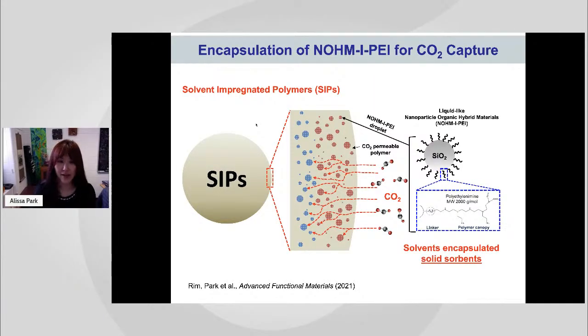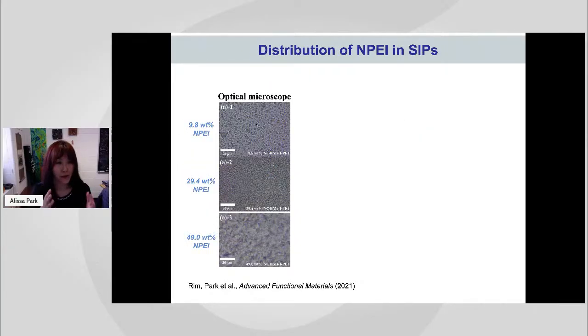We call it SIPs. Now what we do is, instead of using the microfluidic device to make a droplet inside a droplet, we mix the UV curable polymer, before curing, with our NOHMs material. And using high shear, we emulsify this mixture. Now you have micro droplets or sub-micron droplets of NOHMs inside this UV curable polymer. Now you can cast them as a thin film and then UV cure them, so you can massively produce these SIPs materials. When we look at the photograph, we did the loading from about 10 weight percent all the way to 50 weight percent of NOHMs.